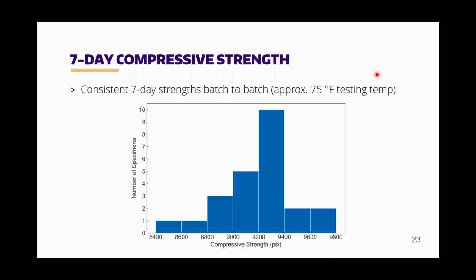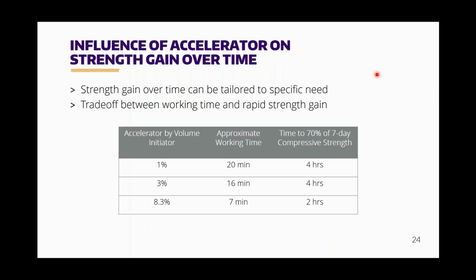Like Travis had mentioned before, the influence of accelerator gives you a trade-off between working time and strength gain. So on the low end, you have about 1% accelerator, that's by volume of initiator. The high end of a working time that you could see is about 20 minutes, so still something pretty rapid. And it takes about 4 hours to get you 70% of your 7-day strength. On the opposite end is an 8%. It brings your working time down to 7 minutes, but gets you that 70% strength in 2 hours.